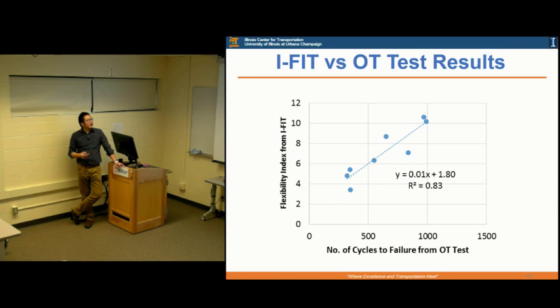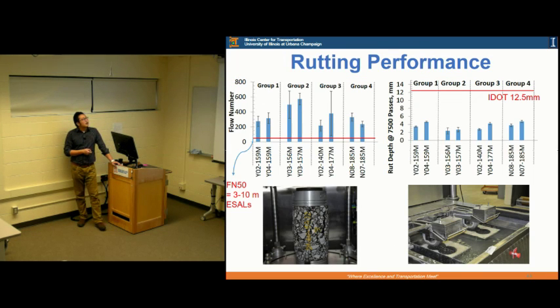So if we actually plot I-FIT versus the overlay tester, we get a pretty good correlation. If you get a higher cycles to failure from the overlay tester, you can also see a higher FI, which means you can use either of those to categorize the cracking resistance of your mixes. Of course, the rutting performance is a little bit different here.